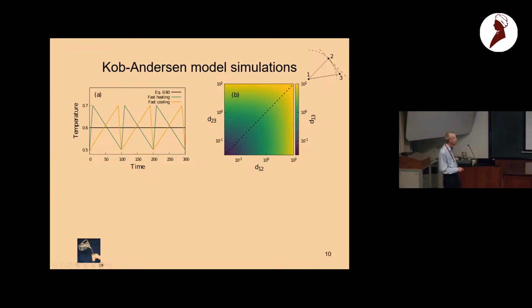What more? We can simulate this, and now we come back to what is the correct distance measure. And the one we used here is the mean square displacement between the inherent states. So you quench to a minimum, and some time later on your path you also quench to a minimum, and then you can calculate the mean square distance between the two minima, and use this as distance measure. Then you get rid of the vibrations.